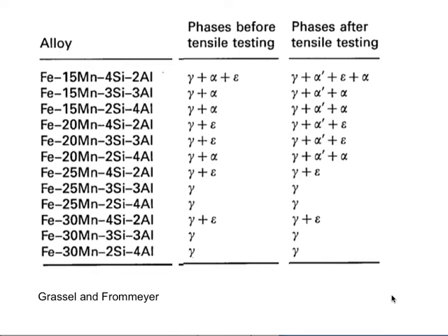Now, the reason for adding 25 manganese is that if the manganese concentration is lower, then you induce various martensitic transformations during pulling. So with 15 manganese, we've got both the alpha prime martensite and the hexagonal martensite, epsilon. And at around 25 weight percent manganese, we begin to get just fully austenitic. When we deform it, all we get is twinning and dislocation movement, right? No phase transformation.